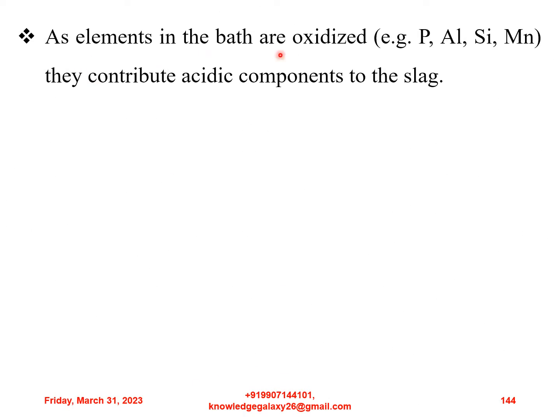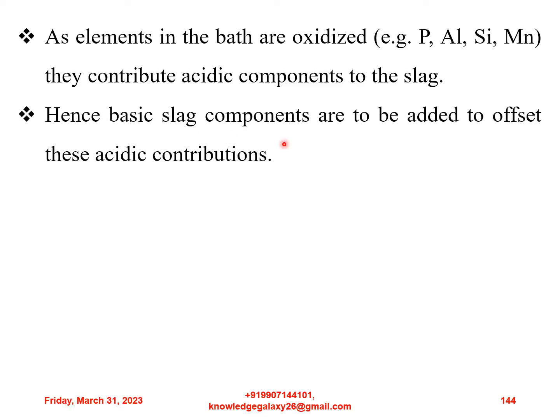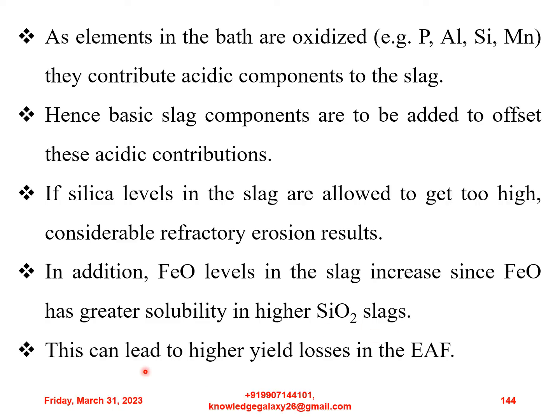As elements in the bath are oxidized, for example phosphorus, aluminium, silicon, manganese, etc., they contribute acidic components to the slag. Hence, basic slag components are to be added to offset these acidic contributions. If silica levels in the slag are allowed to get too high, considerable refractory erosion results. In addition, FeO levels in the slag increase since FeO has greater solubility in higher SiO2 slags. This can lead to higher yield losses in the electric arc furnace.